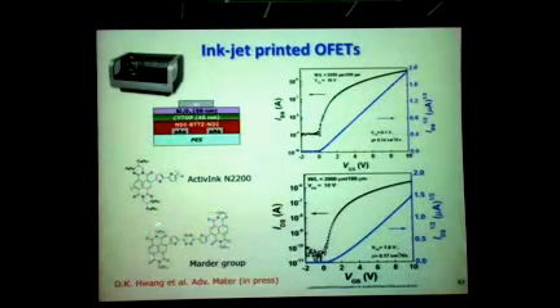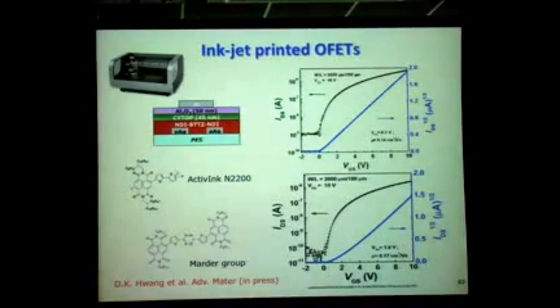This is our latest material, synthesized in Seth Marder's group, a large molecule which is soluble so you can make inks, but it's a monodispersed material - you can reproducibly make exactly the same structure, while with polymers you always have some batch-to-batch variations because you don't always have exactly the same molecular weight.